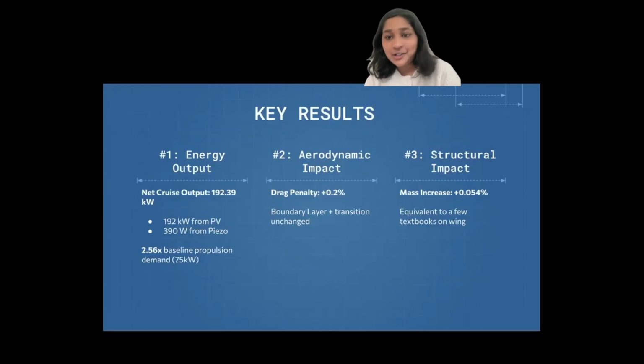The most exciting outcome is a net cruise power output of 192.39 kilowatts. To break that down, approximately 192 kilowatts come from the photovoltaic layer. It performs extremely well under cruise level irradiance, and about 390 watts come from the piezoelectric harvesting. While the piezoelectric contribution is comparatively small, its importance lies in being continuous, vibration-driven energy production that works even when sunlight fluctuates. The drag penalty is remarkably low, just about a 0.2% increase.